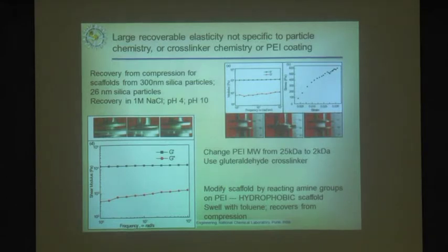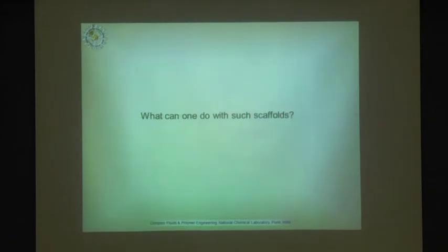Having made the scaffold, these are highly hydrophilic because you have these amine groups on there. You can then modify them to make them hydrophobic, and make hydrophobic scaffolds that you can swell in an organic solvent, and that also seems to display the same kind of behavior. So it really doesn't seem to matter what the chemistry is. Somehow when you cross-link in the frozen state, you create this kind of microstructure that sets the properties that we see in these systems.